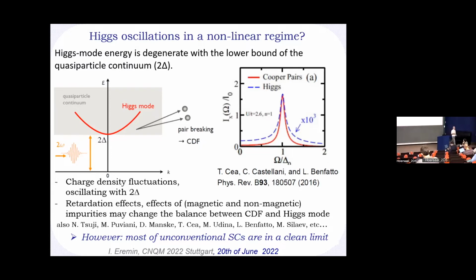There has been continuous discussion whether what you see can still be treated as a Higgs. In fact, if you have disordered superconductors, with non-magnetic or magnetic impurities, you can effectively change the balance between what is called the charge density fluctuation, which is the contribution of Bogoliubov quasi-particles, and the Higgs mode. However, the bad news is that even if in a conventional superconductor you are probably able to change the balance or bring them to a similar order of magnitude,